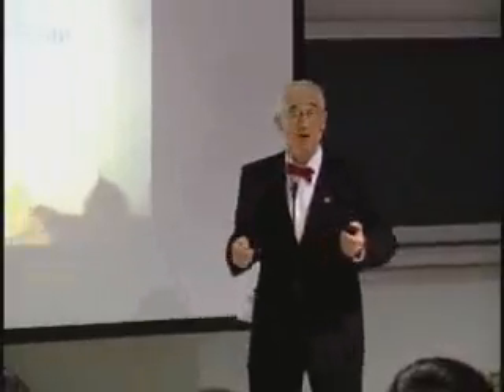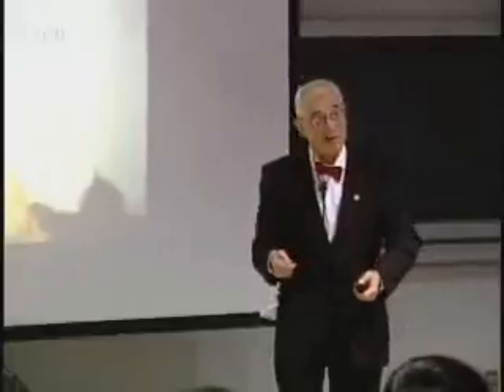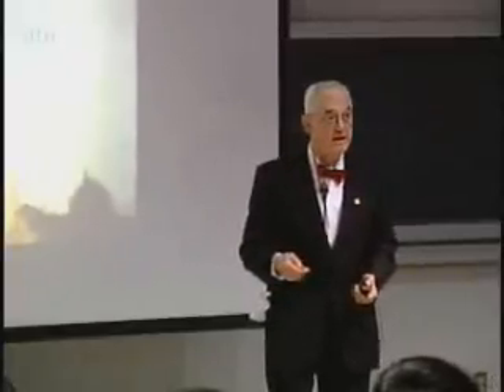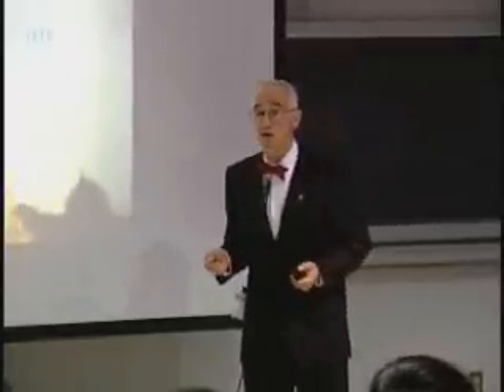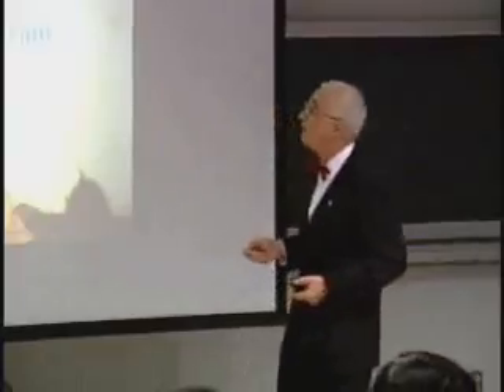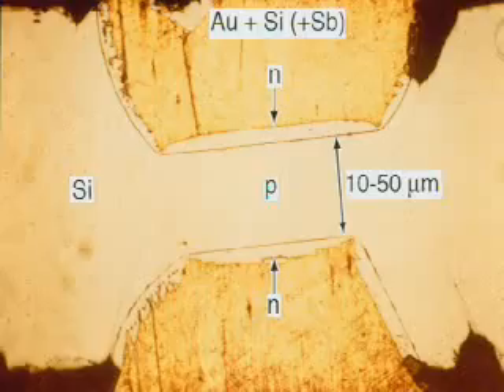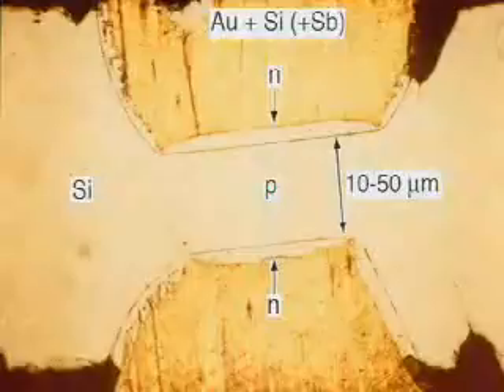He stuck indium on one side thermally, antimony on the other side, and he regrew a so-called alloyed region. And here I have something like that, except I switched to silicon. I didn't make this. Some other guy made this in 1954. He had a P-type piece of silicon that you see here. It wasn't oriented perfectly. You see some tilt here and tilt here.